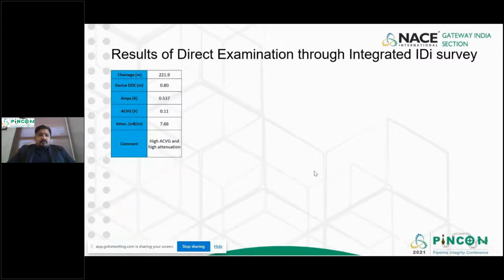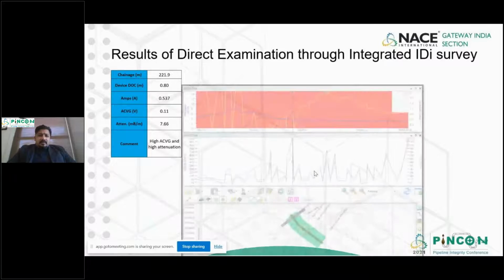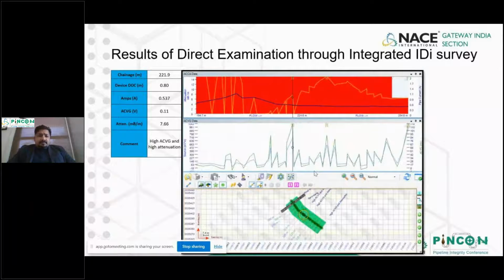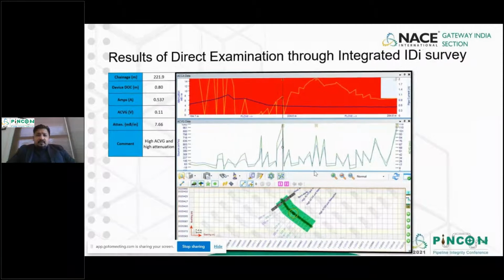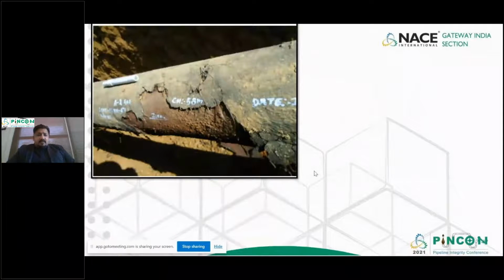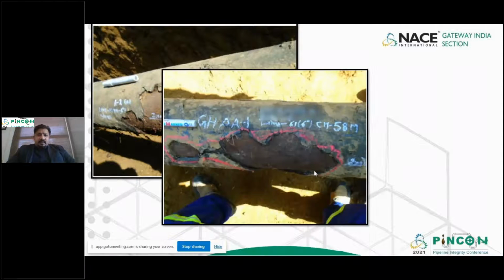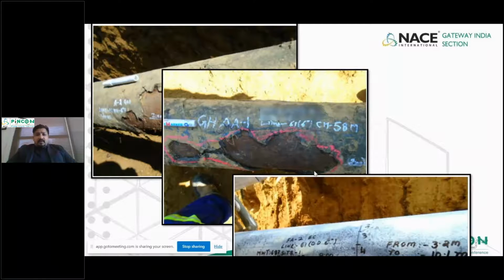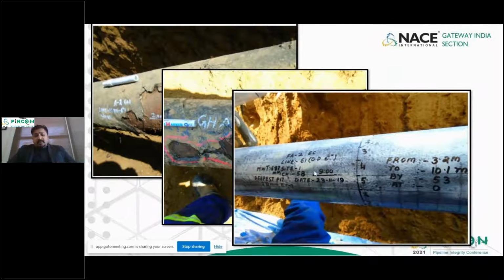So this is one location at 221 meters. We have high attenuation and a peak ACVG fault as shown there. And this is how we see it in the field. We see a coating holiday, another coating holiday, and underneath the coating holiday, we are seeing a lot of external corrosion, pitting external corrosion. So we're actually finding corrosion from these kind of surveys.